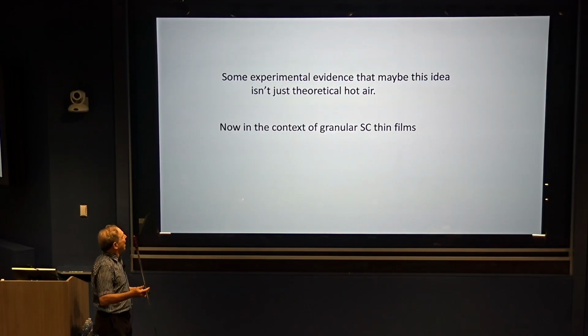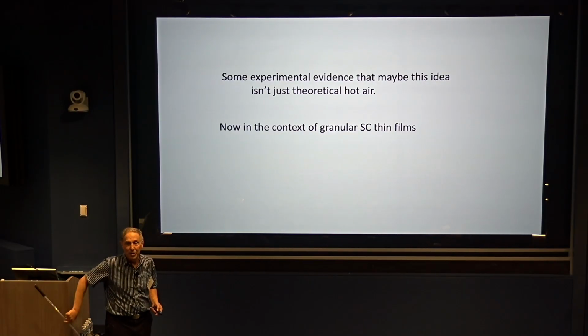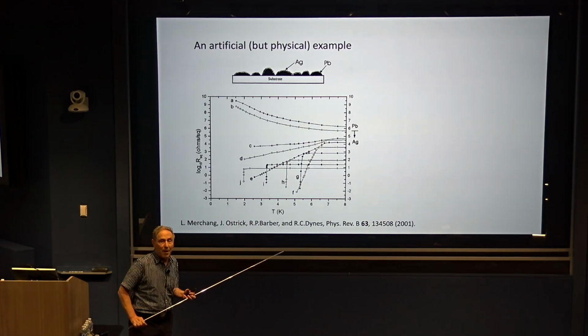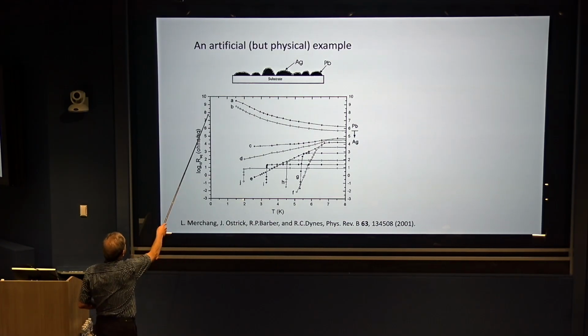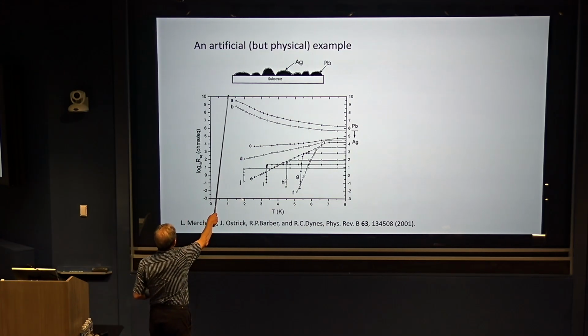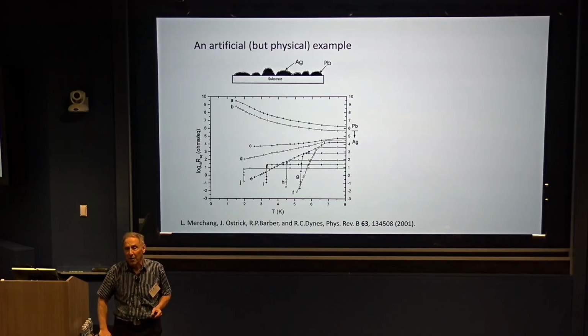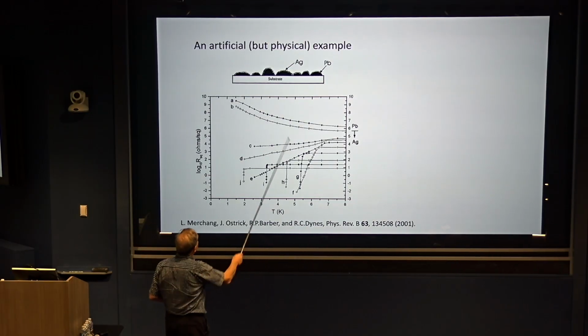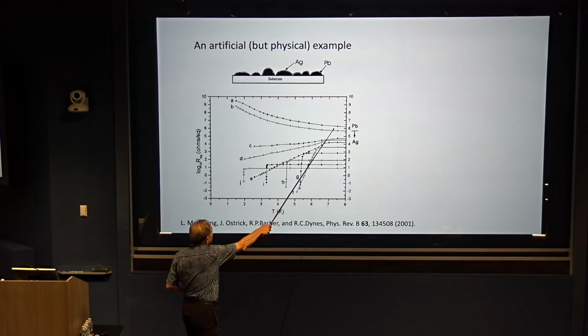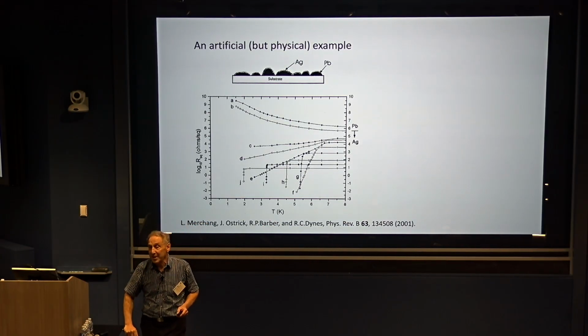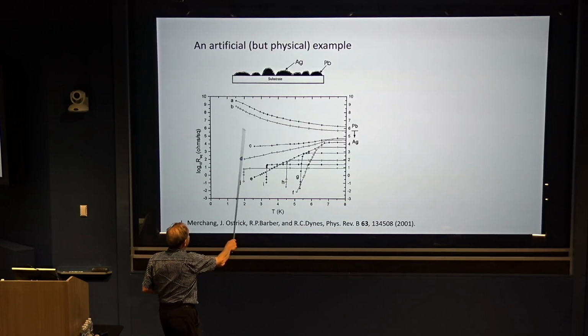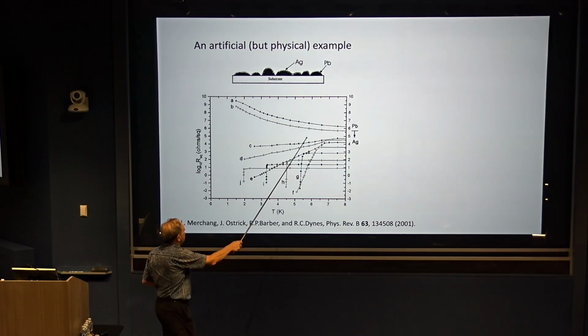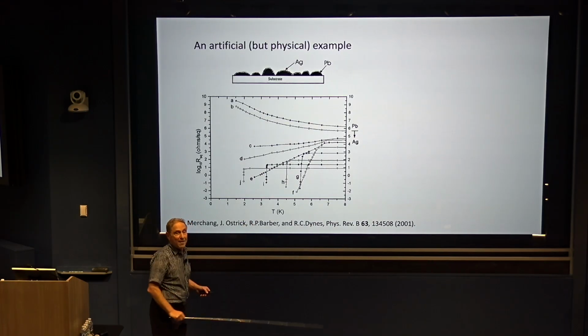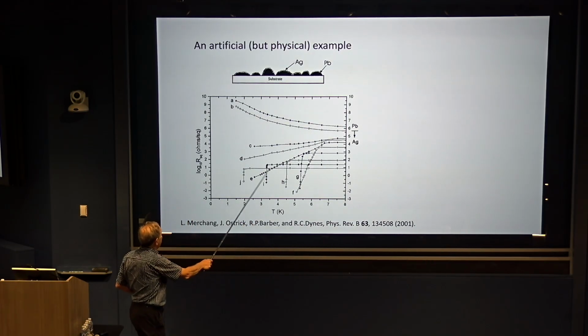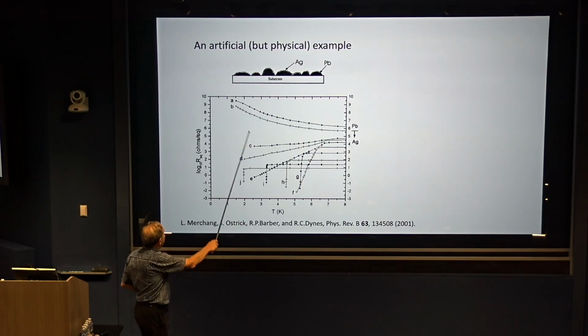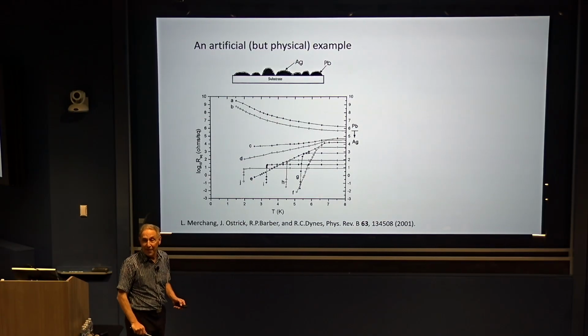Okay. So let me show you how this works in real superconductors. Here are some beautiful old experiments of Bob Dynes, where he took granular lead and then deposited increasing amounts of silver on top of this. Silver is a normal metal, and it also wets. And so in the normal state, the resistance drops smoothly with silver. There's a complicated evolution of the resistance. You can see that something happens at the bulk Tc of lead, at least until you get a lot of silver coming on it, and then you're inducing superconductivity in the system.